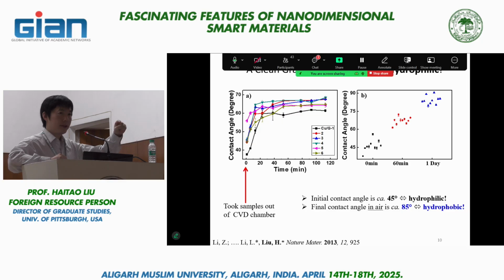So when we make the graphene and we measure the contact angle right away, it's about 45. If we simply leave them in air for about a day, the contact angle will become 90. And the literature said the contact angle of graphene should be around 90. So we can reproduce the literature if we just wait for 1 day.